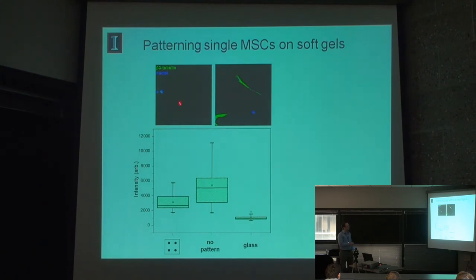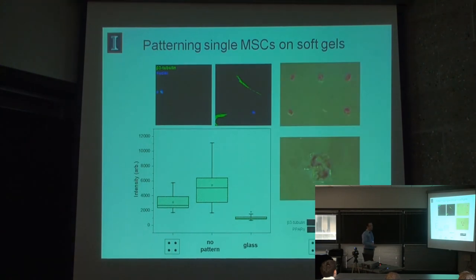So here, when cells are patterned, it's tough to see here, but that's because the marker isn't really there. These are patterned cells, and they show very low levels of beta-3 tubulin. While in unpatterned culture, a subset of these cells will elongate, develop these processes, and start expressing this marker for neurons. And this is quantitated with this box and whisker plot, where we see throughout the spread, there are some of these cells that are expressing higher levels of beta-3 tubulin.